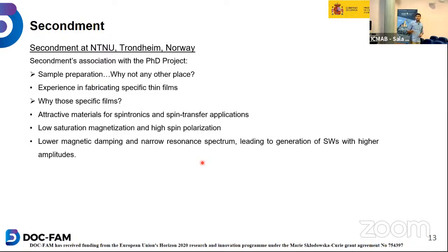Why these films? Because they are attractive materials for spin torque and spin transfer applications, and they have low saturation magnetization as compared to nickel or other ferromagnetic materials, lower magnetic damping, and a narrow resonance spectrum, which leads to spin wave excitation with greater amplitude. So we can see there are more effects in that.